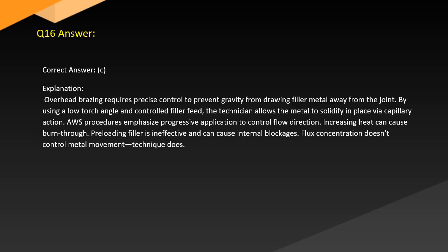Answer. Correct answer. C. Explanation. Overhead brazing requires precise control to prevent gravity from drawing filler metal away from the joint. By using a low torch angle and controlled filler feed, the technician allows the metal to solidify in place via capillary action. AWS procedures emphasize progressive application to control flow direction. Increasing heat can cause burn through. Preloading filler is ineffective and can cause internal blockages. Flux concentration doesn't control metal movement. Technique does.